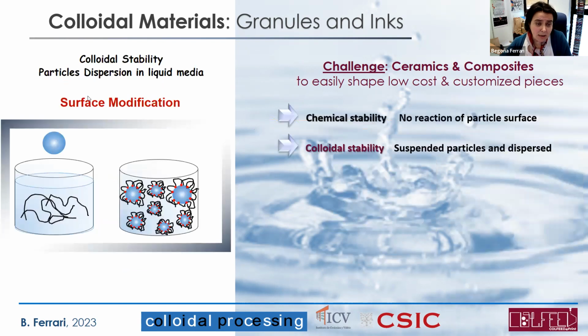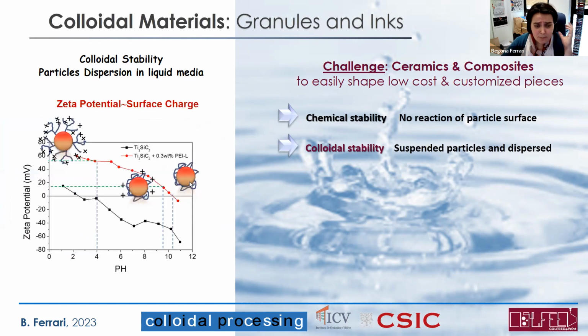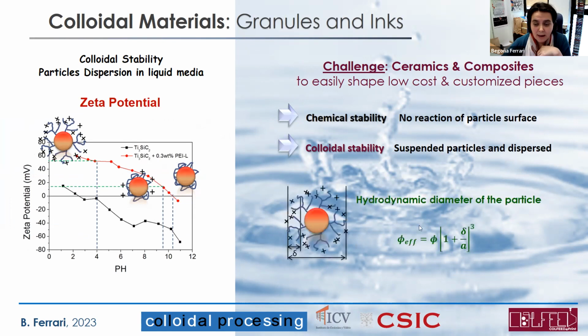And also, we need to talk about the surface modification. We have polymer stabilizers that we can use to cover or change the surface of our particle and achieve the colloidal stability we need to isolate particles and disperse them in the water. This is a very important thing, and the tool that we use for that is the zeta potential. Studying the zeta potential of our suspension or particles in water, we can manage how we adsorb this polymer, and also how this polymer is structured, and the stereochemistry of the polymer is going to influence our packing process. In fact, we need to define what is the hydrodynamic diameter of a particle inside of the suspension.